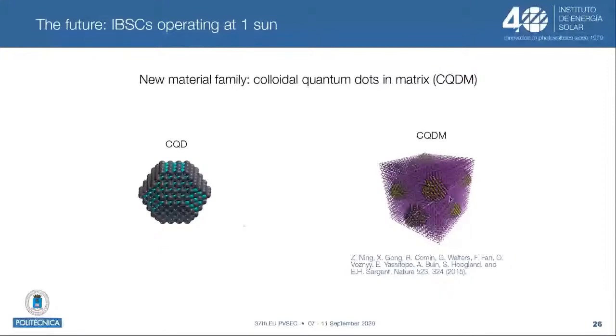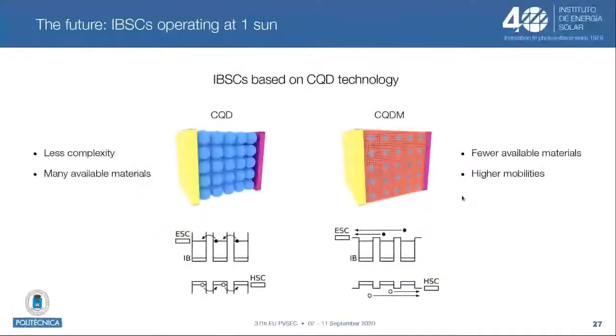And with these two cases, the self-standing quantum dot CQD and the colloidal quantum dot in a matrix, we pictured two alternatives for making an intermediate band solar cell, which would consist simply, in this simple sketch, of sandwiching either of the two materials between electron and hole selective contacts. And we think that both possibilities are good candidates to fabricate IBSCs working at one sun. There are, of course, pros and cons for each of them.